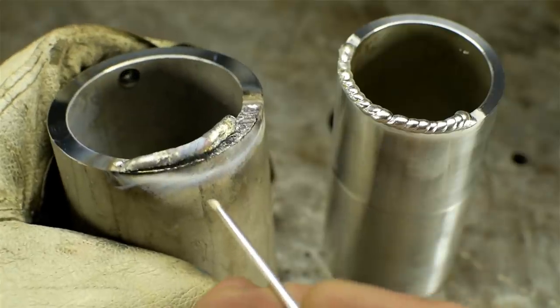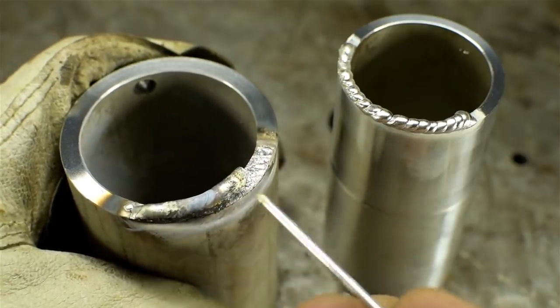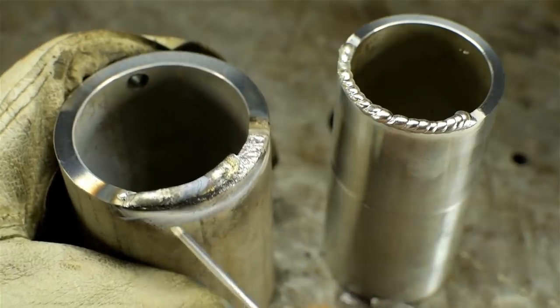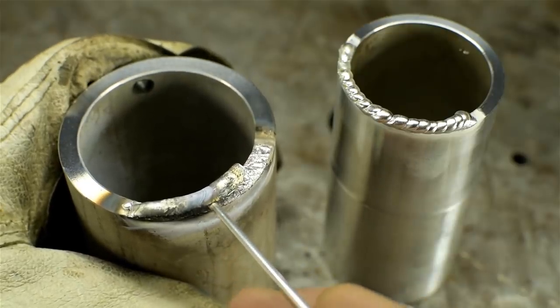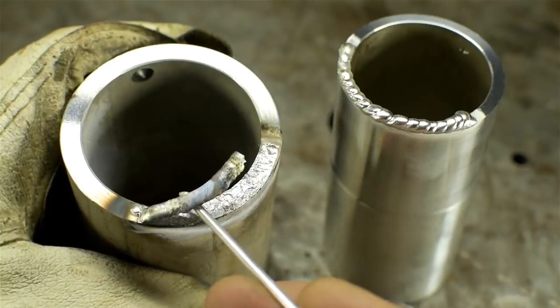I haven't seen the video yet, but hopefully you saw the difficulty I had welding that. There was a lot of spitting coming off the metal, fouled the electrode a couple of times. And that weld bead popped right up.